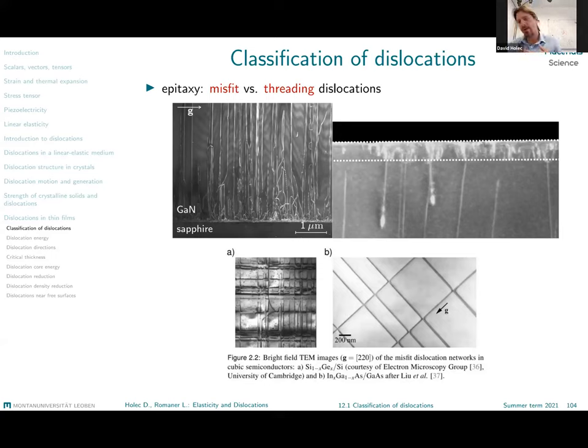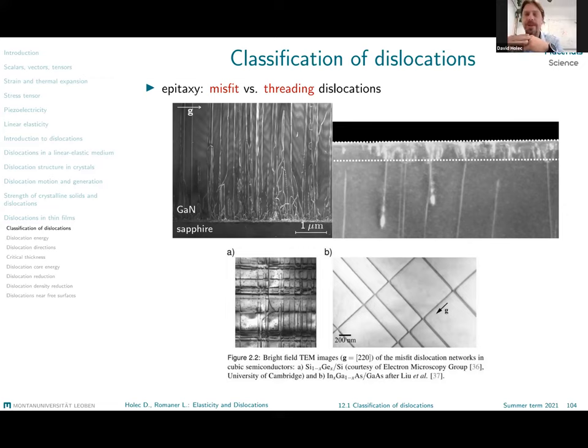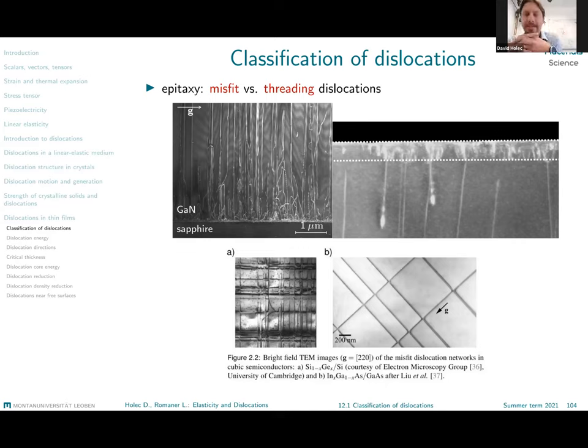As soon as you start overgrowing material epitaxially — meaning that the material in the thin film has a certain crystallographic relation to your substrate — then either the material really grows epitaxially with perfectly aligned crystallographic planes, or because of the lattice mismatch, the overgrown material starts relaxing some lattice mismatch, which leads to the misfit strain. It starts relaxing by generating misfit dislocations.